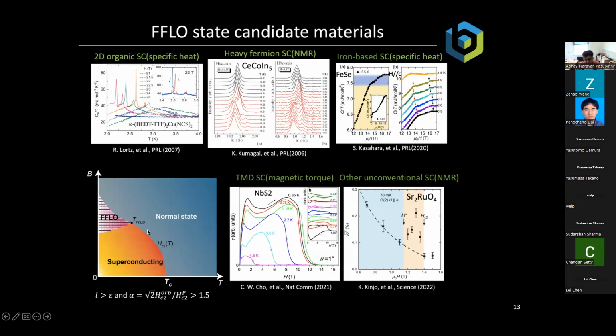And so generically, if you ask yourself, where would this FFLO state show up in a measurement, you want to be at low temperature, but at high magnetic field. And just before the material turns into the normal state, one might expect a little bit of this FFLO state to appear. And so a number of different experiments have been performed to look for this. I think there's some evidence of this in a number of different materials. I put down some of these here. Basically, the experiments either look like thermodynamic measurements, where you look at heat capacity, looking for multiple transitions, or there are measurements like, for example, NMR, where the idea is that if I have a non-constant gap in space, then the different regions would give me different signals in NMR. And so I would see, for example, two lines, two peaks in NMR that is indicative of this kind of modulated superconductor in real space.